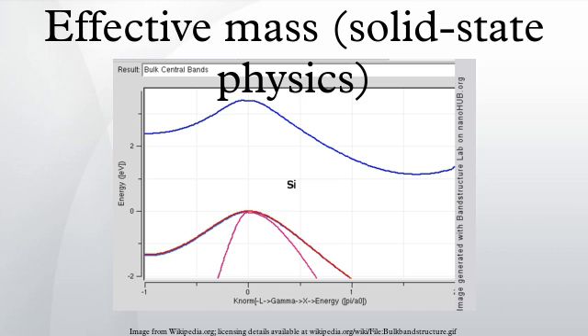Significance. The effective mass is used in transport calculations, such as transport of electrons under the influence of fields or carrier gradients, but also is used to calculate the carrier density and density of states in semiconductors. These masses are related but, as explained in the previous sections, are not the same because the weighting of various directions and wave vectors are different. Certain III-V compounds such as GaAs and InSb have far smaller effective masses than tetrahedral group 4 materials like Si and Ge. In the simplest Drude picture of electronic transport, the maximum obtainable charge carrier velocity is inversely proportional to the effective mass. The ultimate speed of integrated circuits depends on the carrier velocity, so the low effective mass is the fundamental reason that GaAs and its derivatives are used instead of Si in high bandwidth applications like cellular telephony.